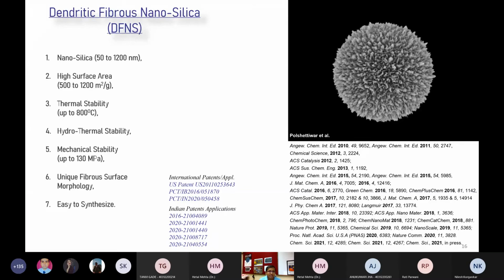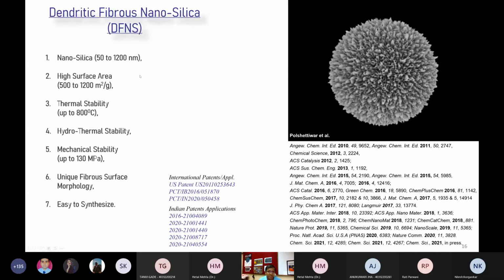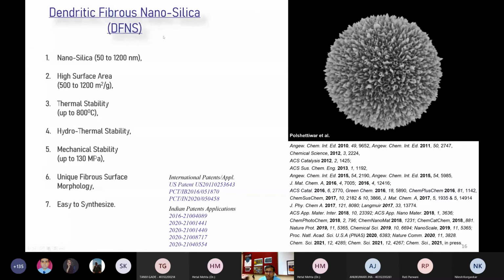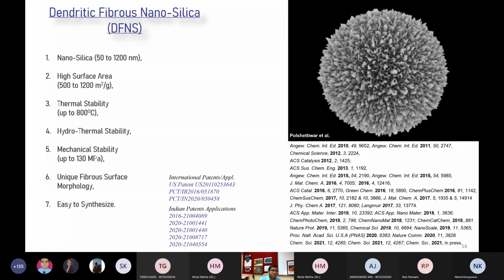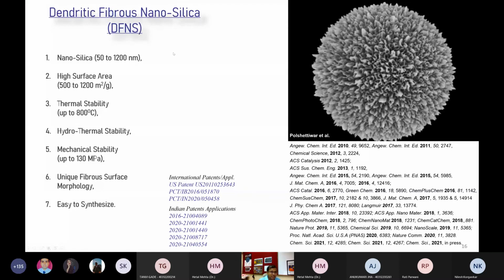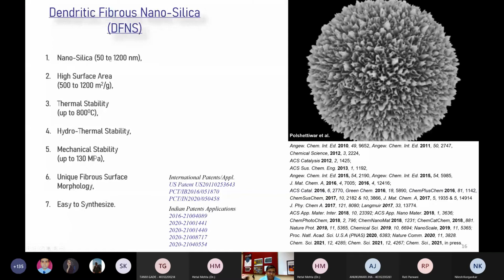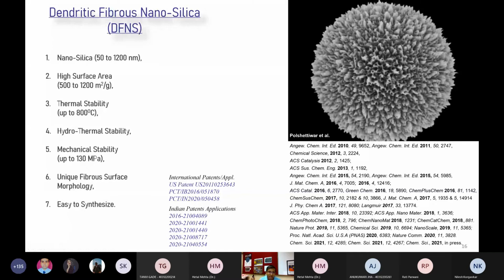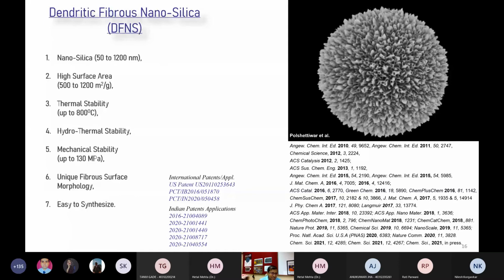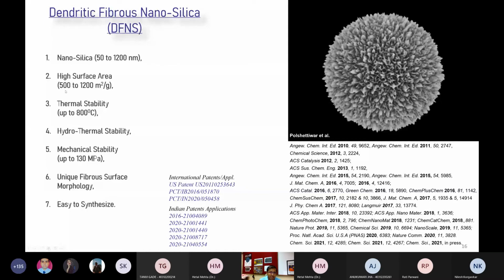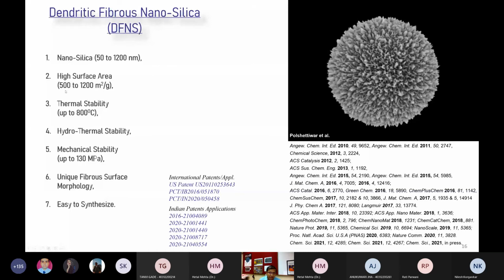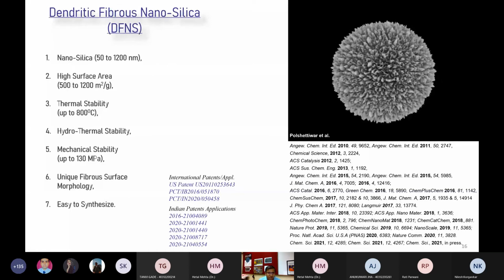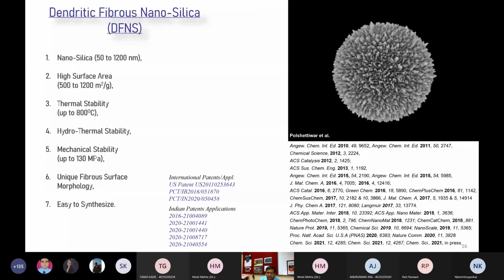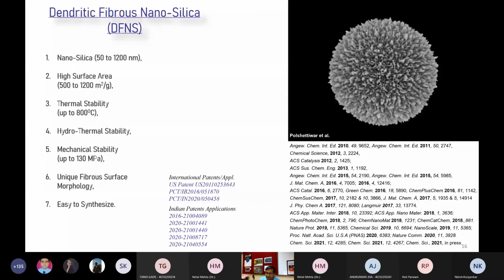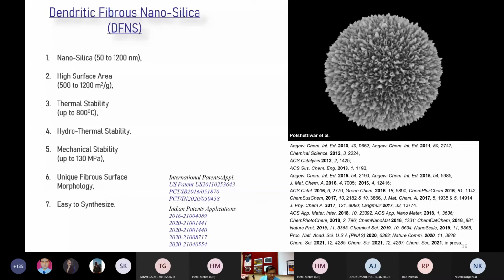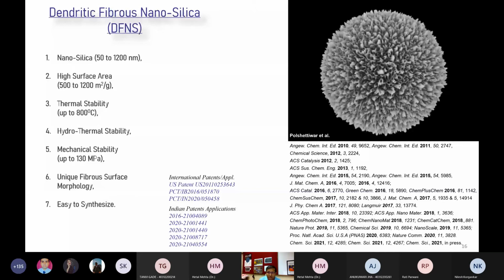So in our lab, we developed this high surface area material. This is called nanosilica, which has this dendritic fibrous morphology, and that's why we call them DFNS. One can tune the particle size, say from 50 to 100, 100 to 200, 400 to 600. You can get different particle size ranges. It has high surface area, 500 meters squared per gram. It's like if you take 1 gram of a powder in your hand, it's like one football ground. So huge surface area, and you can use that to generate active sites onto that surface, or some other basic sites, acidic sites, hydrophobic, hydrophilic, and do different functions using that material.